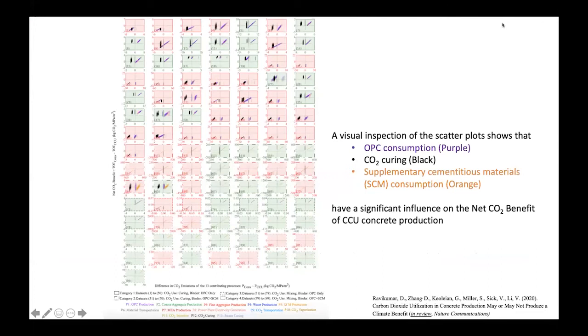So we repeated this step of analysis for the 99 data sets. And what we get is three key findings from the 99 data sets. Initially, a visual inspection of the scatter plots shows that the amount of cement consumed, the amount of energy required to cure with CO2 in CCU concrete, and the amount of supplementary cementitious materials, that is materials apart from ordinary Portland cement which are used as binder materials, in orange. So purple, black, and orange, as you can see here in most of the graphs, are the most important parameters, 3 out of the 13 parameters. They have a significant influence on the net CO2 benefit. This is just a preliminary analysis, a visual inspection, but it's not quantitative in nature.